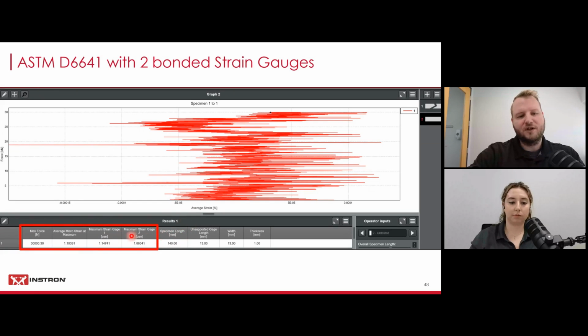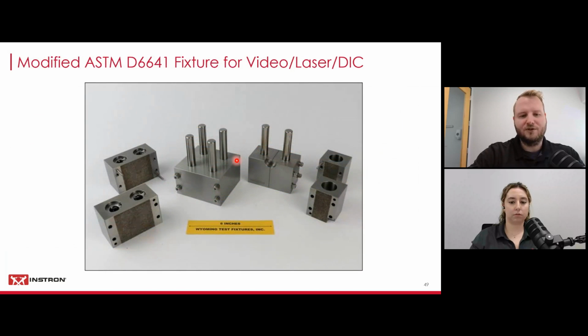But yeah, then you get the strain readings of both extensometers, which you could also plot, and you can already see here that we are really in the 1 microstrain area. So I had to change the units to microstrain to even be able to display them. And then you can average the results from those two, and you can also make an averaged graph, which is the one that we're showing here. So you can look at them individually, or you can use the averaged one in the middle. So very, very low strain for these unidirectional materials, which is one of those characteristics of composites, right? Very stiff materials.